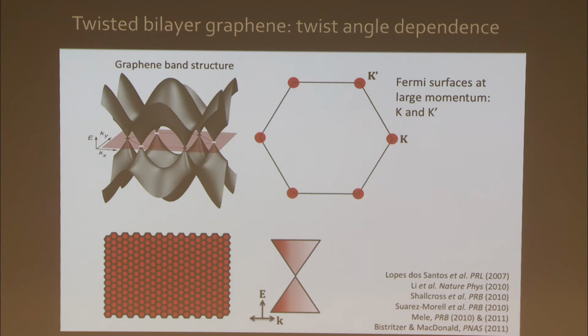So this is graphene. This is the Dirac cones of electrons in graphene. This is the electronic structure. This is just a zoom in of this. This is the reciprocal space, the Brillouin zone. And if we have a finite number of electrons in graphene, our Fermi energy would be up here. And this would be the Fermi disks at K prime points, the Fermi surfaces. Now, if we put another graphene sheet on top, and it's perfectly aligned with the previous one, then you have both Dirac cones of layer 1 and layer 2 on top of each other. The reciprocal spaces are on top of each other. Everything is aligned, okay?